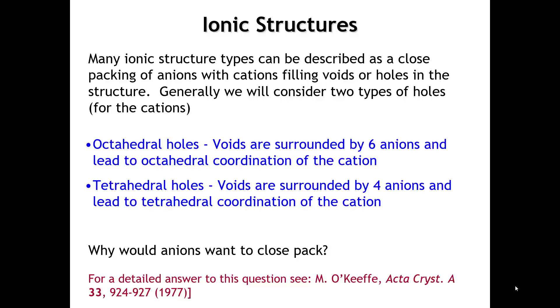Here's the short version: the arrangement of spheres in a box is the same whether we want them as close together as possible or as far apart as possible. If they're as far apart as possible they might not be touching, but they would still adopt the same pattern as a close-packed arrangement. If we constrain the volume and put anions as far apart as possible, we want them equally spaced—and that equal-spacing arrangement is symmetrically equivalent to a close-packed arrangement.